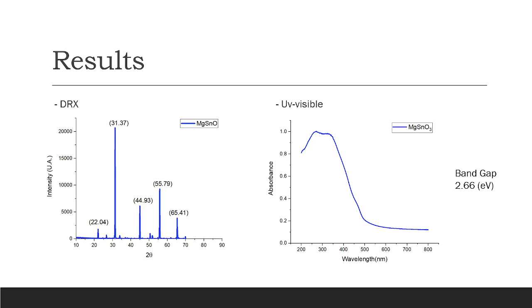Then we have the UV-visible spectrophotometry. It's a quantitative technique used to measure how much a chemical substance absorbs light. Absorbance spectra of the magnesium stannate nanoparticles were recorded using the PerkinElmer Lambda 900 UV-near-IR spectrophotometer in the range of 200 to 800 nanometers. Then we can use the Tauc plot with this graphic to find the band gap of the semiconductor. We do the calculation and obtain that the band gap is 2.66 electron volts.